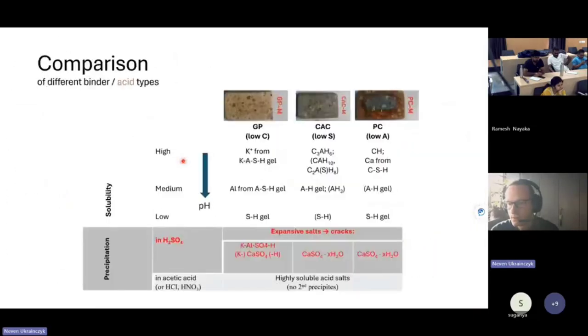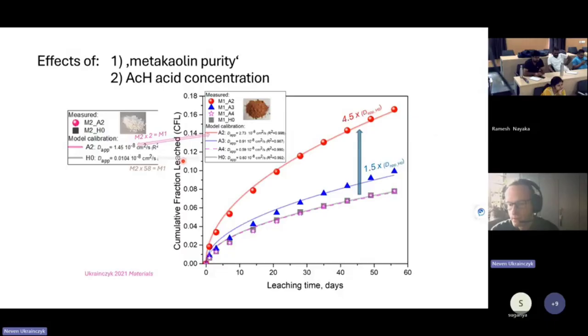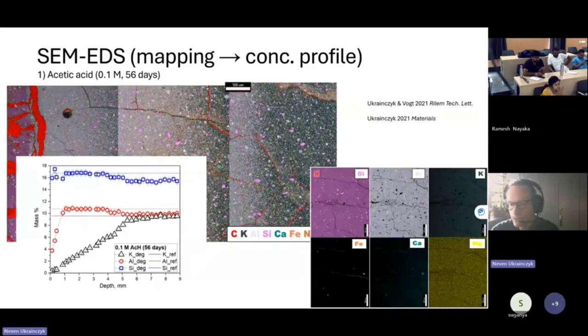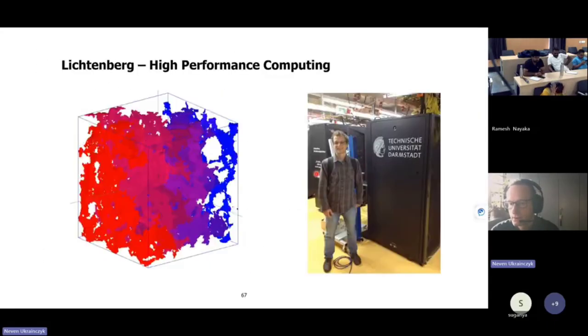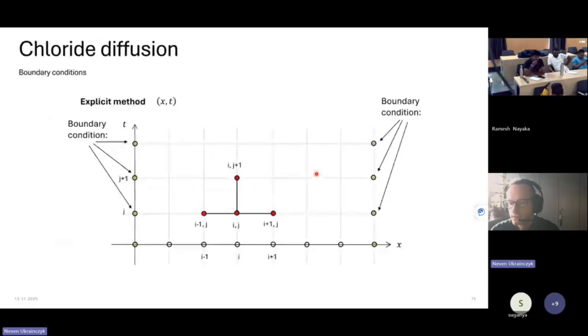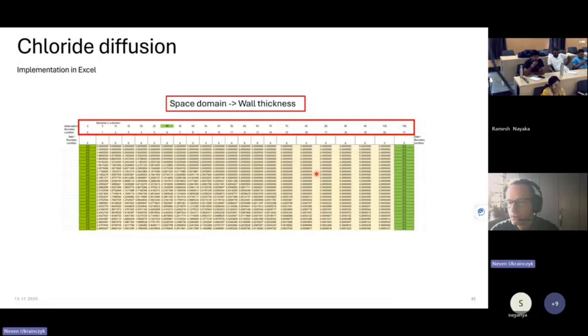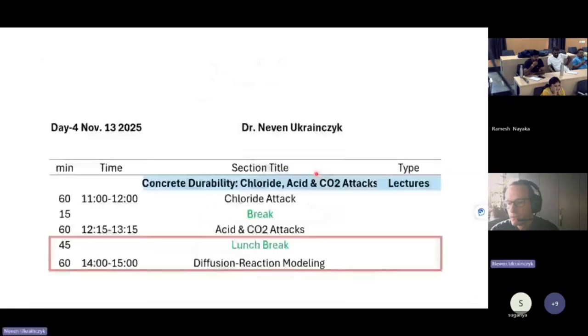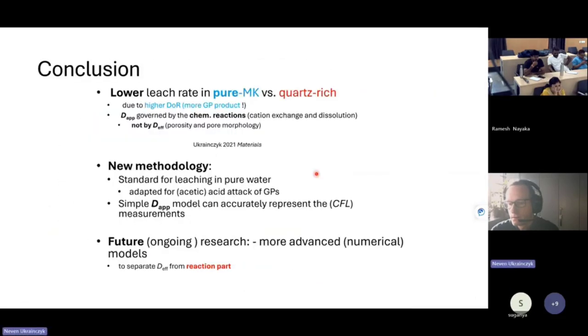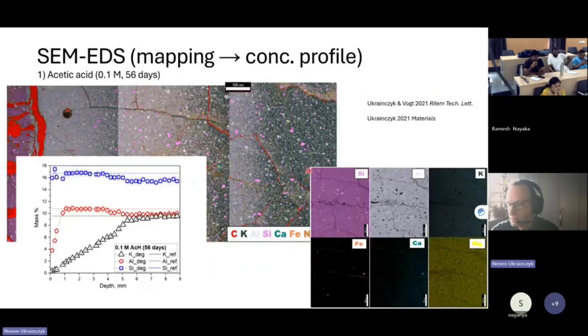What we have in our lab is just normal EDS, which we are very happy with. But you cannot really get chemical composition per pixel because the signal is very low, and that's why we need to take this many pixels to get a good signal that we can fit. But then we have to do it in the software, so actually we have to do it manually, unfortunately, to get this kind of nice profiles.